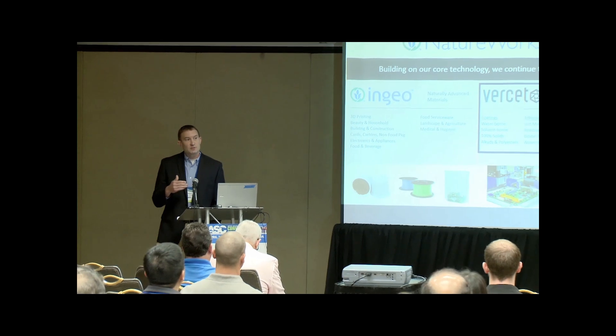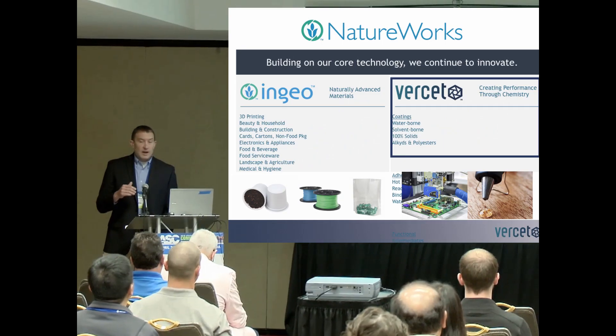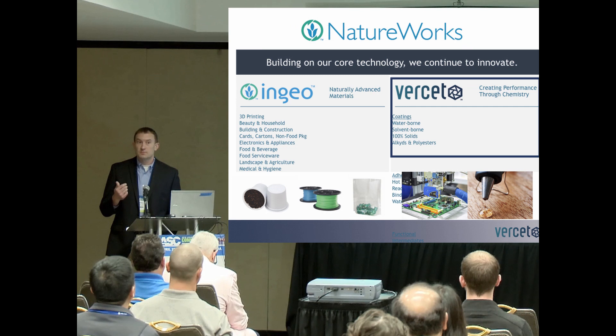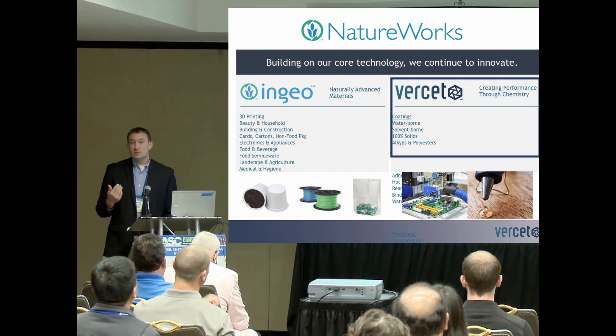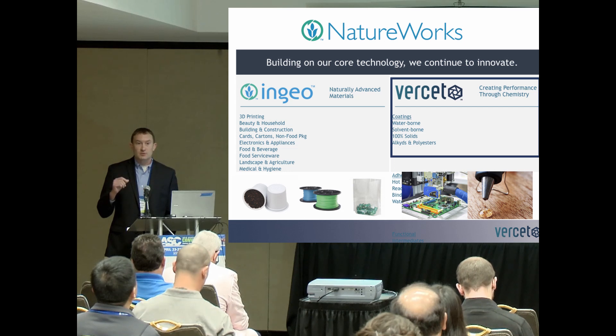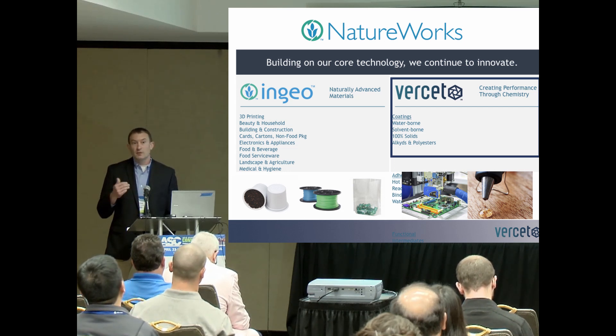NatureWorks is based upon polylactic acid technology. The established resins are of a high molecular weight, high viscosity, semi-crystalline nature. These materials are designed to be injection molded, formed into sheets, films, fibers, suitable for applications such as 3D printing, food service ware, food packaging, and other household goods. Where NatureWorks is innovating is in a lower molecular weight, lower viscosity, amorphous PLA material, more suitable for applications such as coatings, adhesives, and other functional intermediates.